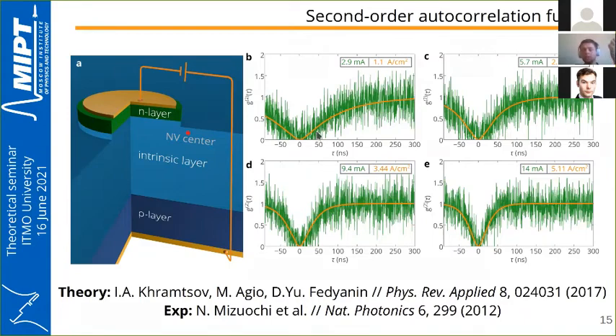reproduced the G2 function at different currents through the diode, and compared it to the experimental result. It can be seen that the predicted G2 functions reproduce well the experimental ones at different pump currents. Moreover, they explain the strange dependence of the dip width on the current, which was previously unknown. Since one diode parameter, the donor compensation ratio in the n-type layer, was not known, it was impossible to reproduce the dependence of the single-photon electroluminescence rate on the current, on the G2 function.